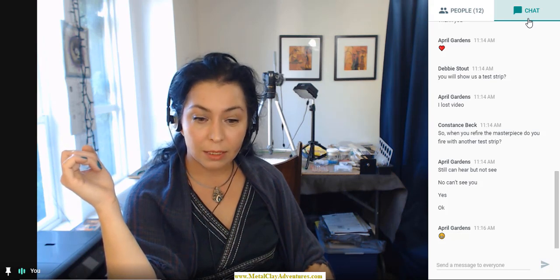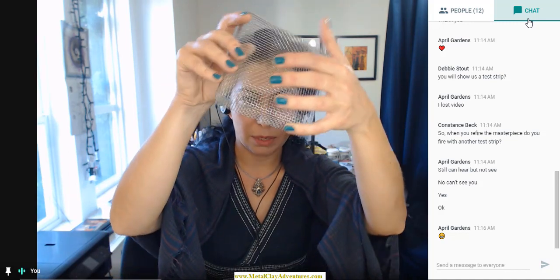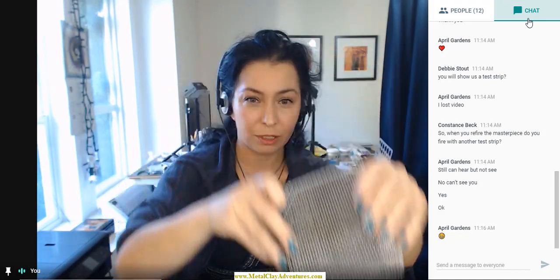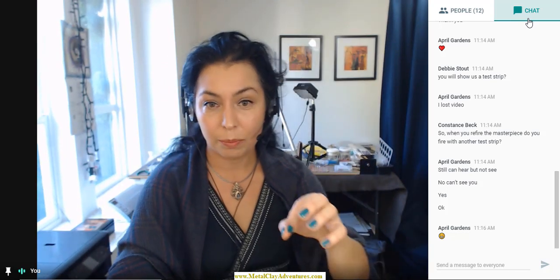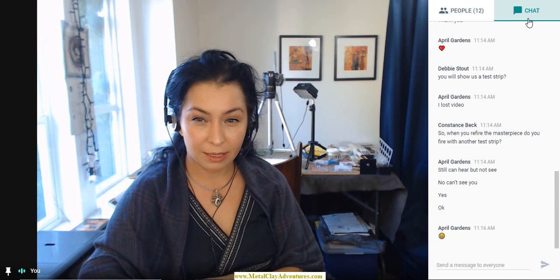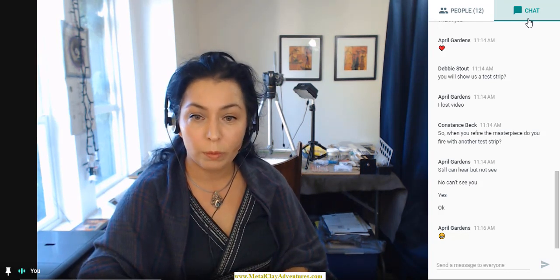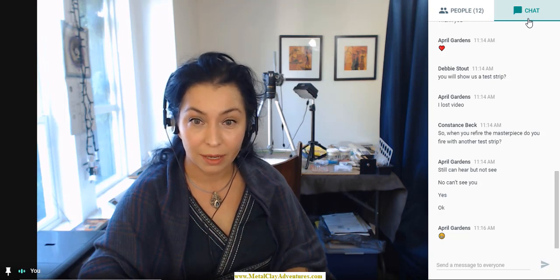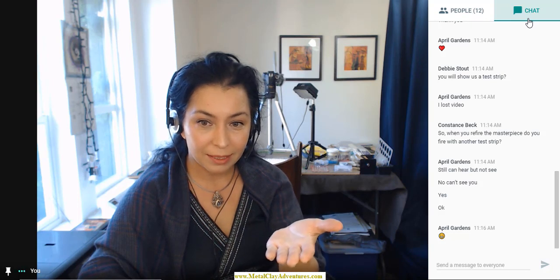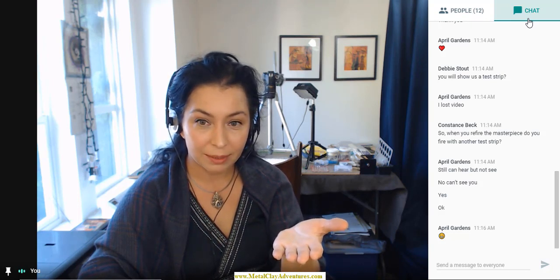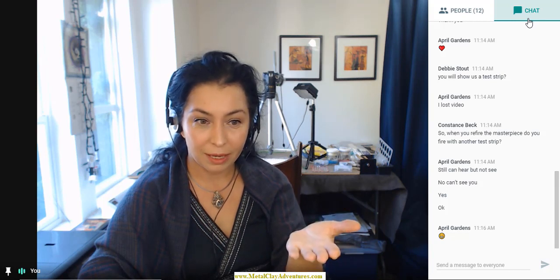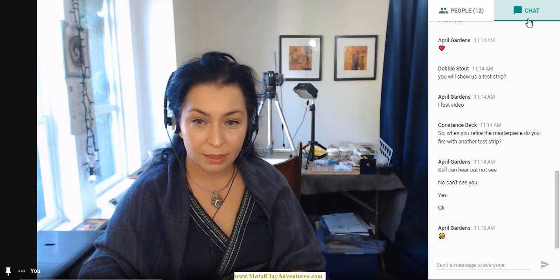When firing air exposed, you don't need to use steel mesh every time as recommended by the manufacturers. You can just place your piece on the carbon. Just keep in mind that the temperatures for the first phase are always less than 1000 Fahrenheit. Why? Because at 1000 Fahrenheit, the carbon will take fire, and you'll not burn off the binders from underneath the piece. So first phase, always air exposed, always temperatures less than 1000 Fahrenheit.